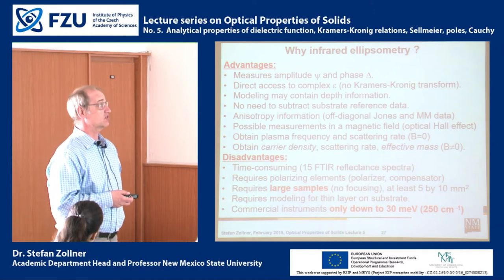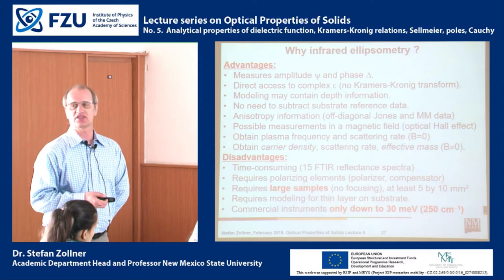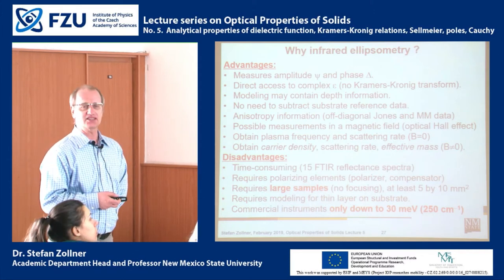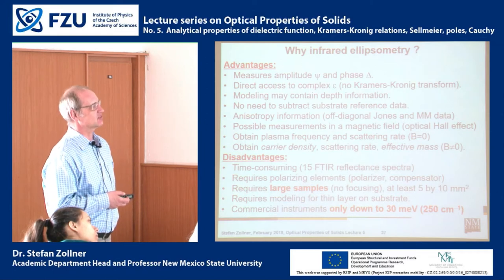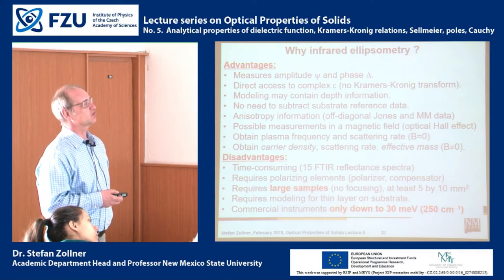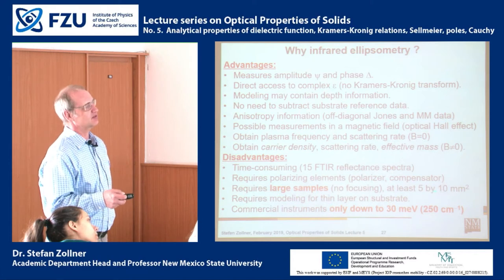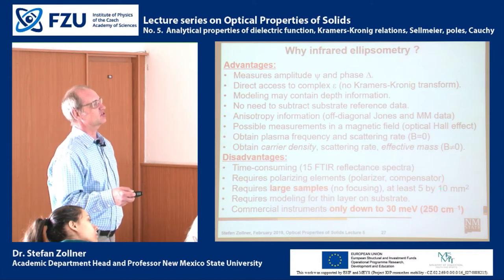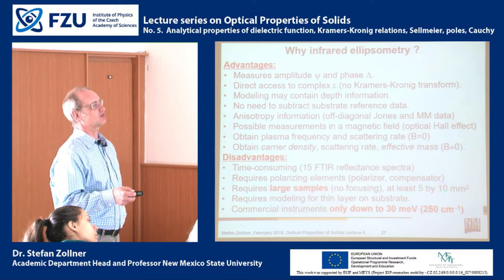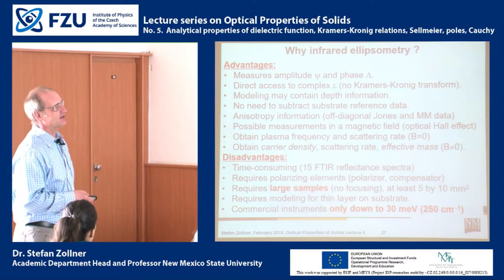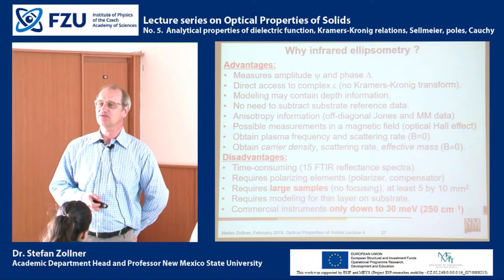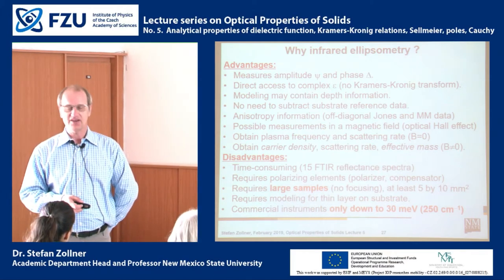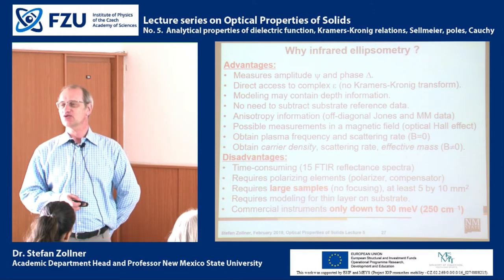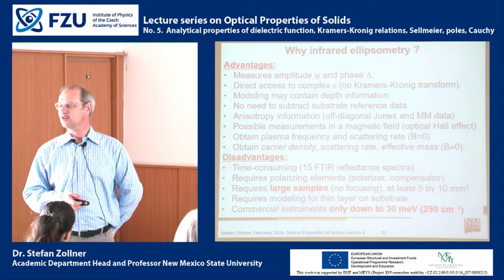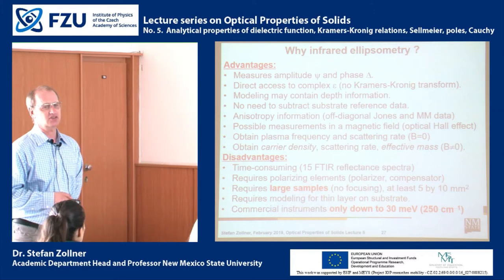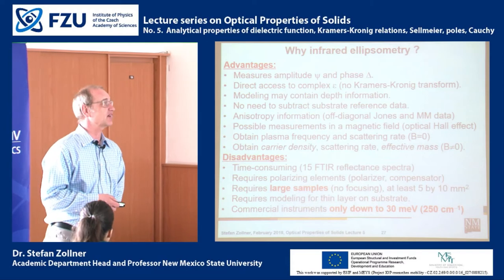There are commercial ellipsometers used in manufacturing where the light is focused down to a 30 micron spot size, but these instruments are not as accurate as instruments where there is no focusing. So we need large samples, and the smallest samples that I've measured here on the infrared ellipsometer with good results were about 5 by 10 square millimeters. 5 by 5 would be tricky. But if you have a single crystal of some not-so-common substance, which is only 10 microns or 100 microns large, then you're much better off doing reflectance with an infrared microscope.